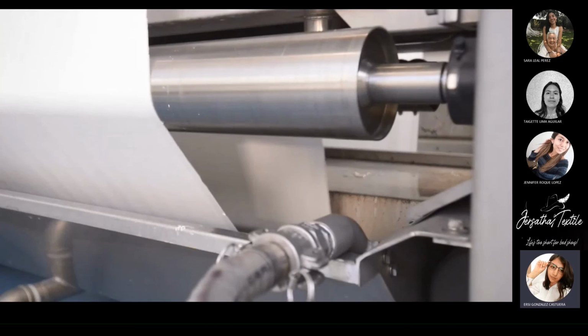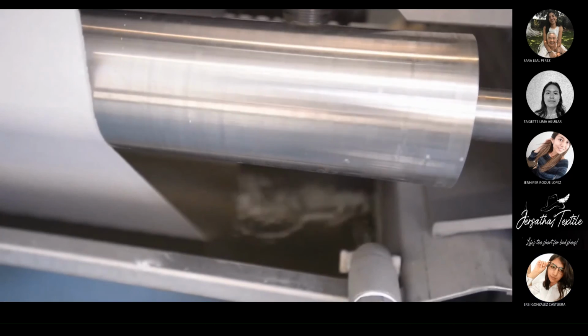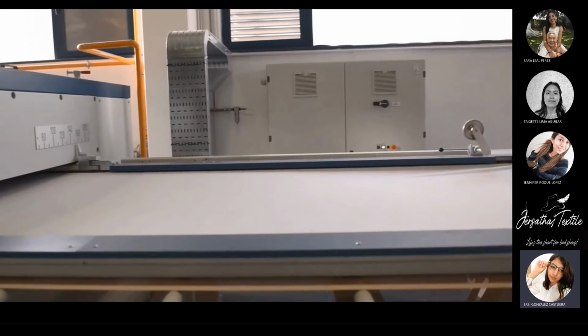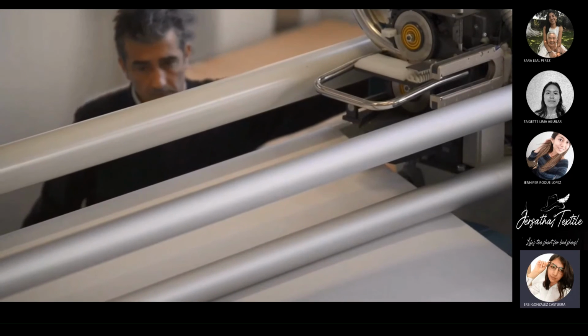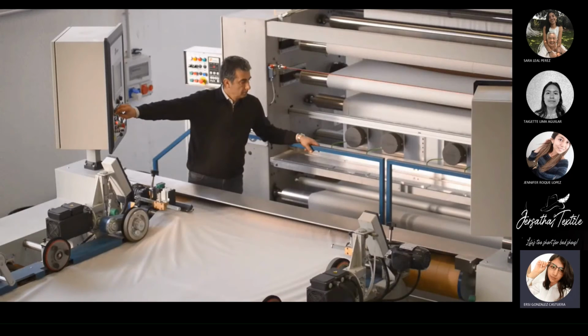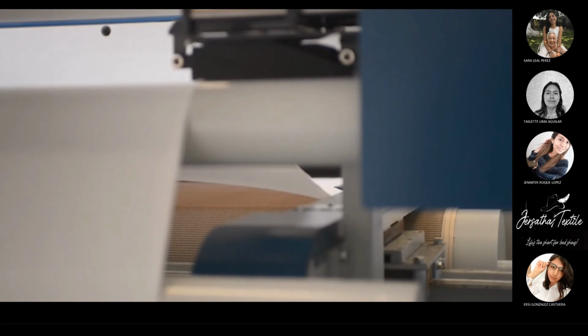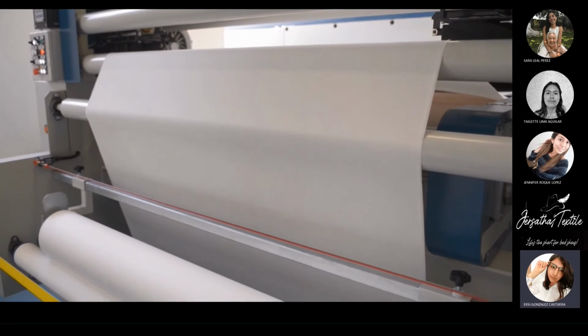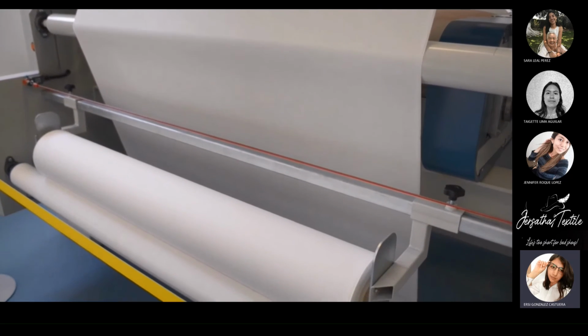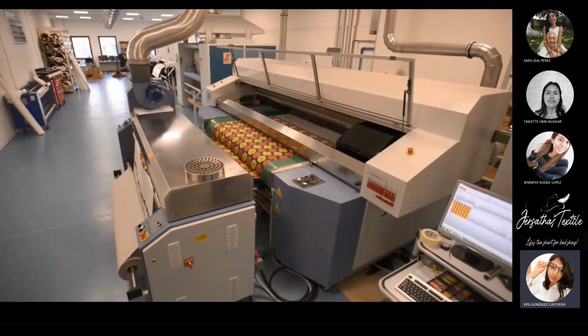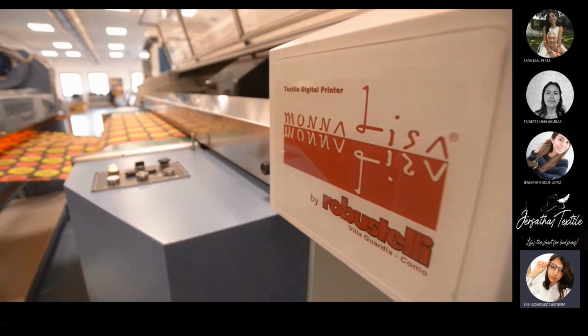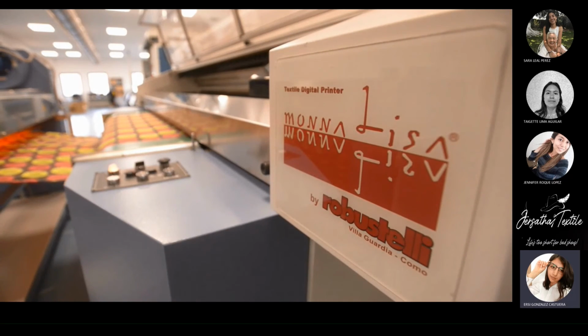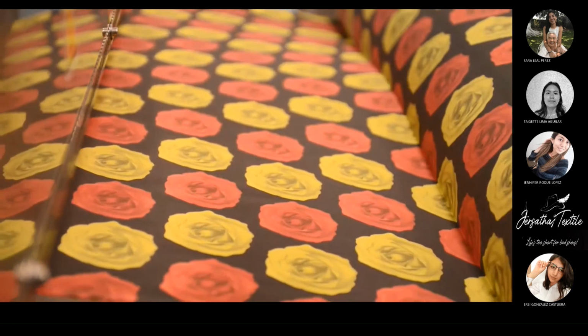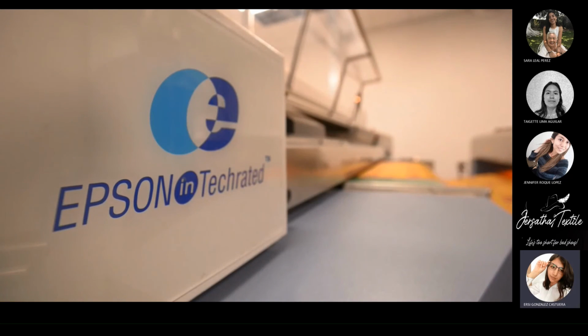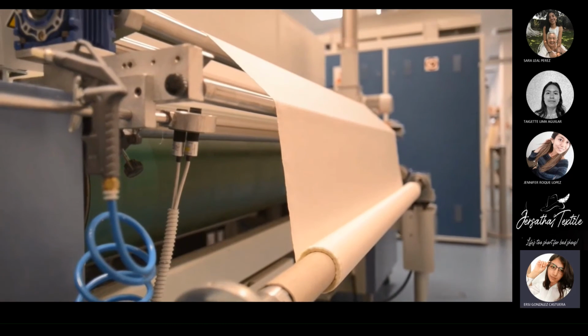The rinses are given to remove the product that was not fixated on the textile surface, and it is done in the open width washing machine, starting with the neutralizing bath with acetic acid at 60 degrees Celsius, and the next rinses are given at 80, 60, and 40 degrees Celsius.